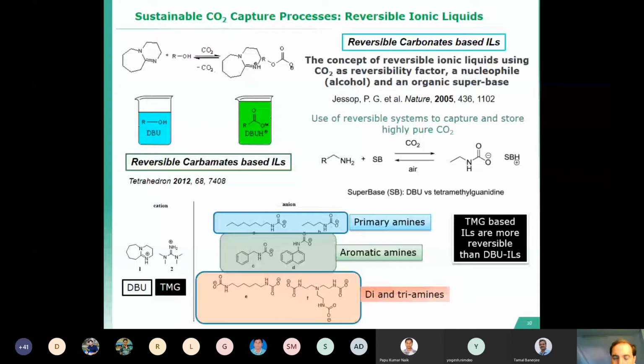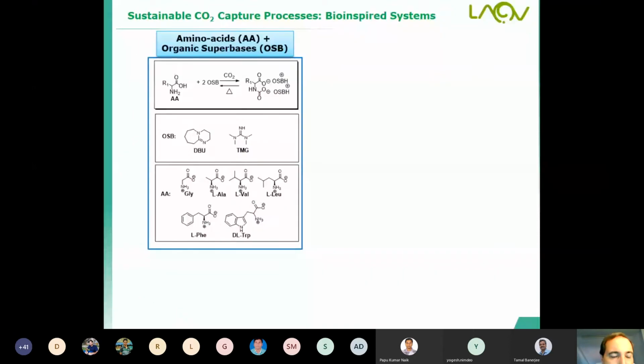But if it's possible to use amines, it's also possible to use amino acids. And we tried to explore different kinds of amino acids, like alanine, valine, leucine, phenylalanine, tryptophan, and others, again in the presence of DBU and tetramethylguanidine, using two equivalents of the organic superbase, because here we have a carboxylic acid and an amine. We need two equivalents in order to prepare these reversible carbamates in the presence of CO2. These carbamates are inspired by natural sources. They are chiral, and it's of interest again to capture CO2.